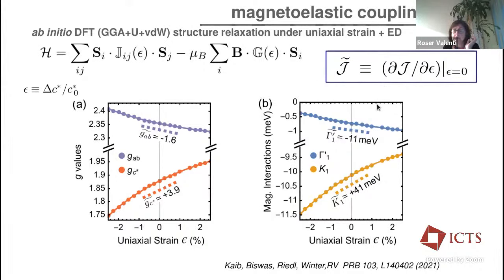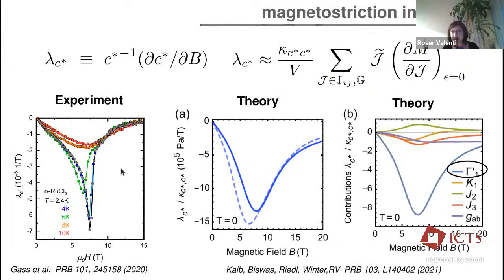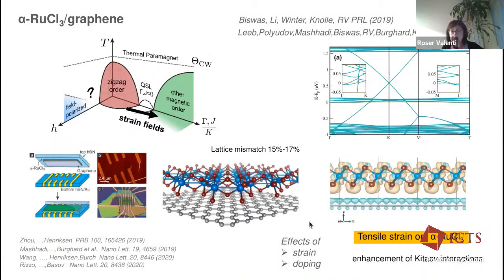And to see that this type of calculation has anything to do with reality, we compare, for instance, with magnetostriction experiments from Dresden. The magnetostriction is basically the response of the lattice when you apply a magnetic field. What one observes is that when you come into this transition where the zigzag is suppressed, the lattice has a very strong response to that. And this is what this magnetoelastic coupling shows. And these are here the theory calculations with these models that I was showing to you, which indeed describe this effect properly. What is interesting is which anisotropic interaction is the one contributing to this effect.